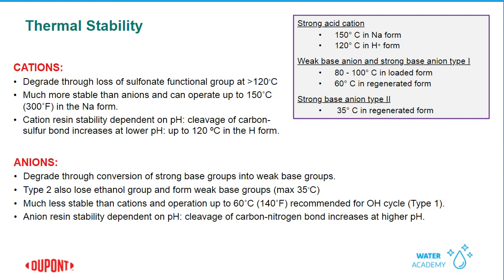Resins exposed to higher temperature will change. They will age faster at higher temperature than they do at lower temperature. So the higher the temperature you submit them to, the lower the lifetime you can expect from the resin. And at those high temperatures, that kind of degradation rate is quite high. And as Donna also explained, if a cation resin is suffering from thermal degradation, it will release the active groups. So that means that acids are added to the water. So using resins at high temperature, you need to take special care how to do that and how to manage that.